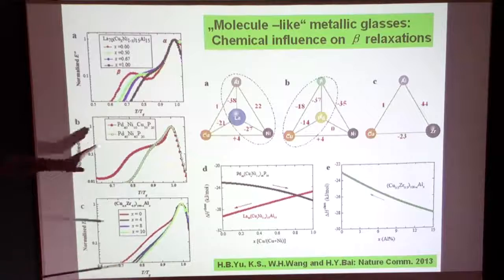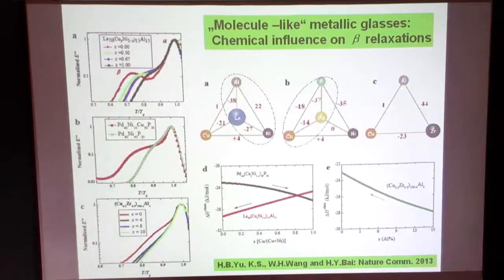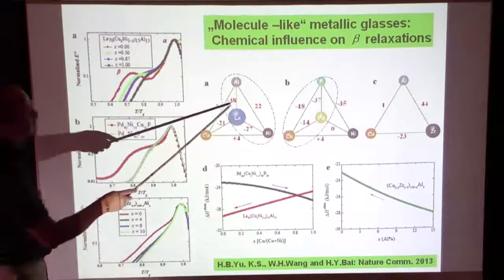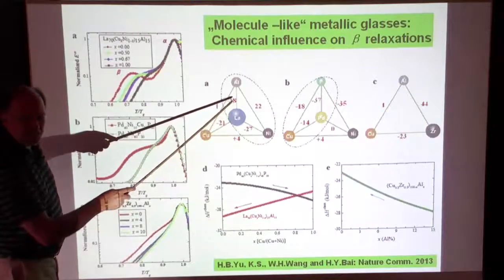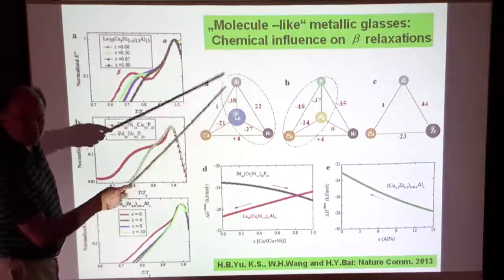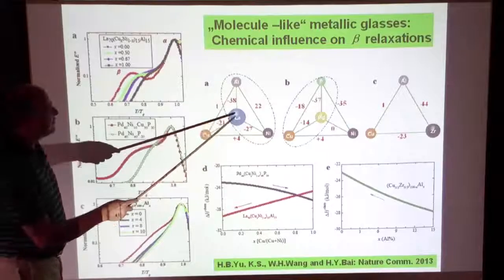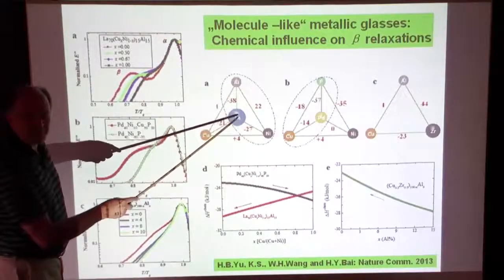So type A and type B depend very much on what kind of element you add and how much you have, what kind of matrix it is. And it means you form structures in the glass, in the liquid already, which are then extended or less extended, like a polymer which you cut into certain segments. So what do the red numbers mean? That means the heat of mixing in kilojoules per gram atom, which is typical for the material science community. This is the strength of the bonding between the two elements.